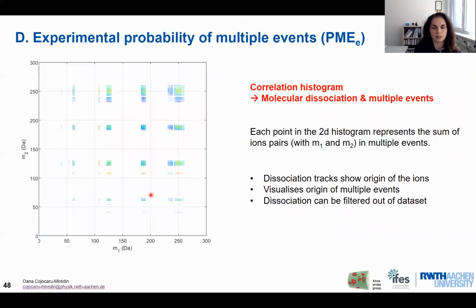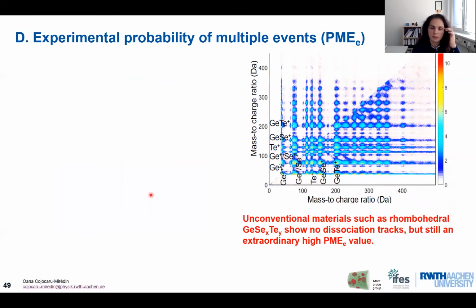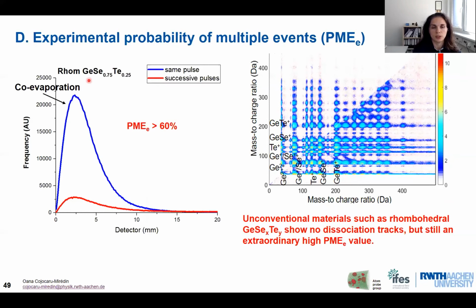And what we get is a correlation histogram, which we will look at. Then we can extract back the number of the multiple events which are not related with the dissociation phenomenon, but only with the co-evaporation phenomenon. This concept has been used to determine the probability of multiple events for materials which have shown very high values. This is the case for the rhombohedral germanium selenium telluride, where the experimental probability of multiple events was found to be higher than 60%. In this case, we don't see any more two humps. We just see one single peak, which corresponds to the co-evaporation phenomenon. And we see also that these multiple events are also correlated in time, but much more weakly than the ones correlated in space.